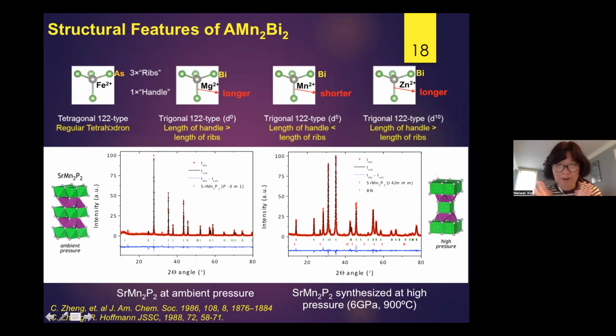When I read that part, I thought maybe we should test using high pressure to see what will happen. So we started from strontium manganese 2 phosphorus 2. Because when I have an idea, I want to test it quickly, we just put it into high-pressure synthesis, in a multi-anvil system. We pressed it at 6 GPa, 900 degrees Celsius for half an hour, just to see what would happen.